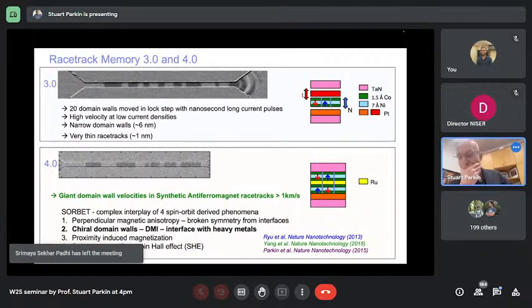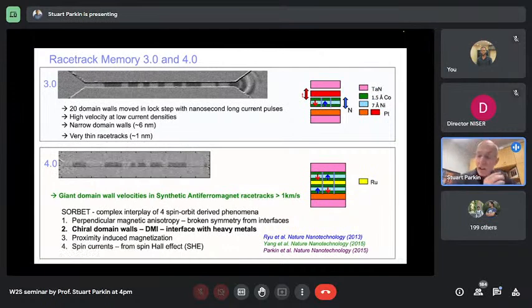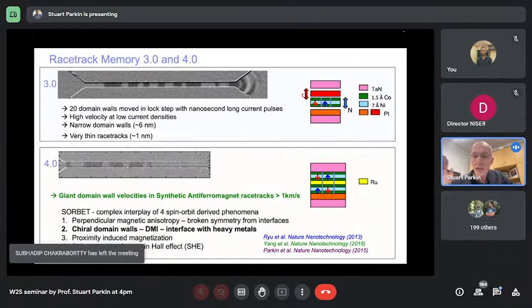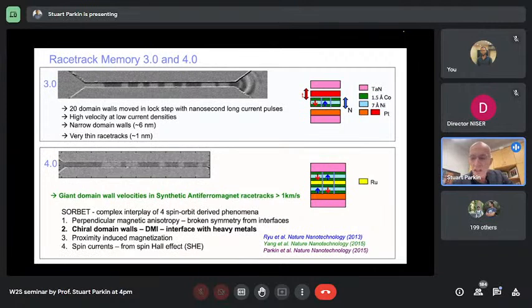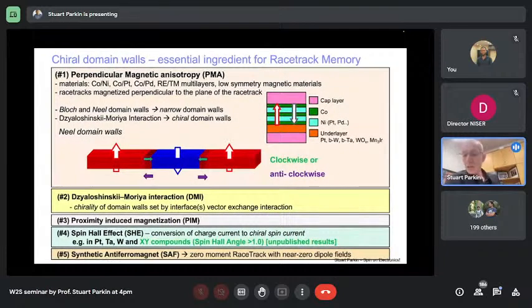Now, as an aside, I'm not going to say too much about three-dimensional racetracks, but we're working very hard to make these types of structures by a special technique, atomic layer deposition, so we can deposit the racetracks not horizontally, but on vertical walls. And we've recently, we believe, achieved that. And therefore, we now have a means of making vertical three-dimensional devices, the devices that I proposed more than 20 years ago. So again, I think we're running out of time, unfortunately.